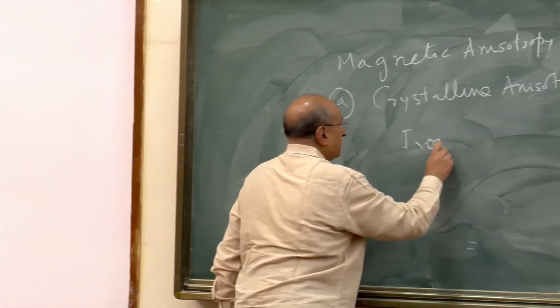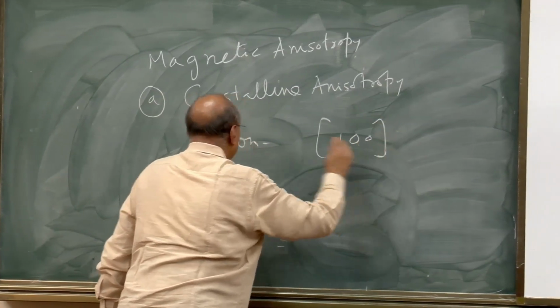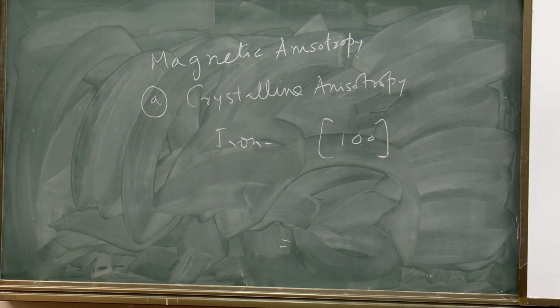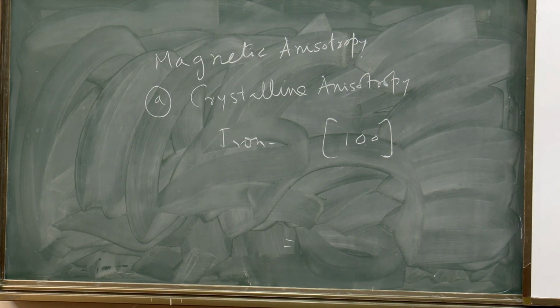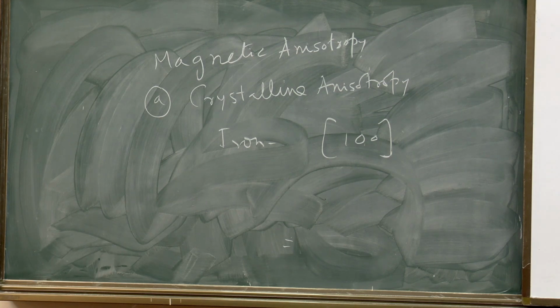Again, this might have been taught earlier. For example, if you take iron, 100 is the easy direction. But in a cubic crystal, there are 6 equivalent 100 directions. This is 100, opposite to that is also equivalent 100. This is 010, but it's also an equivalent 100. There are 6 equivalent 100 directions, and all of them have to be easy. You cannot differentiate between 100 and 001, because what you are calling the x-axis, you could have called the y-axis.